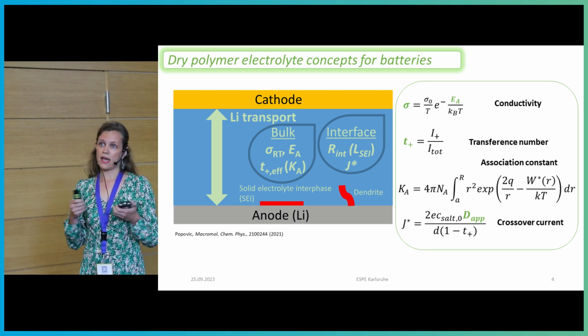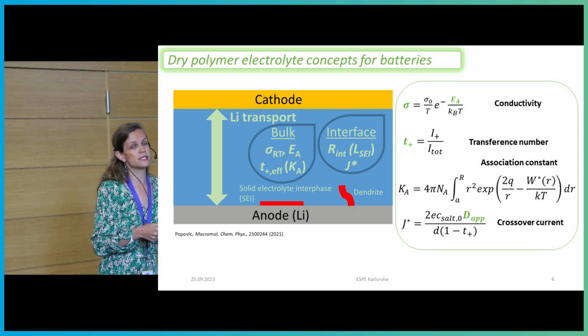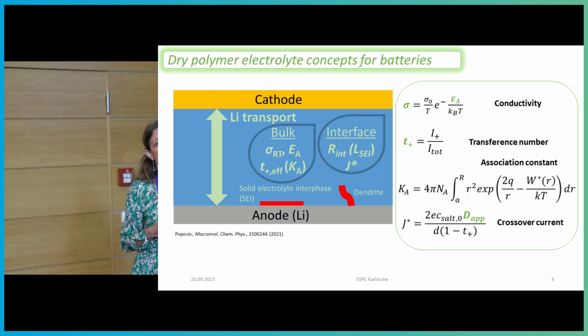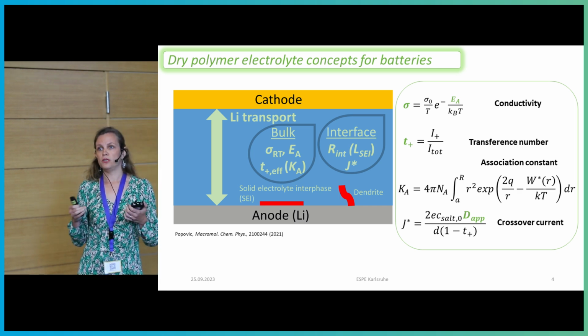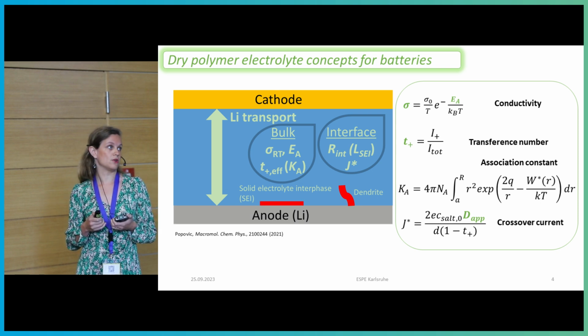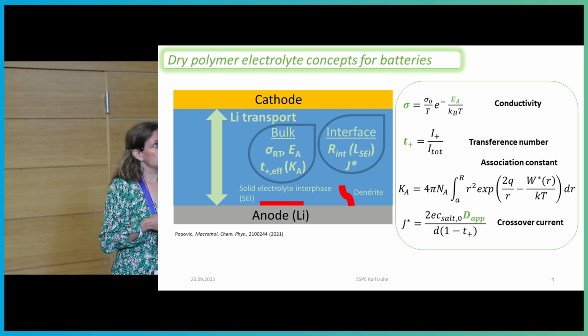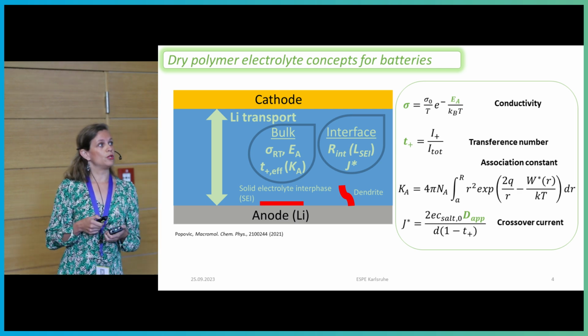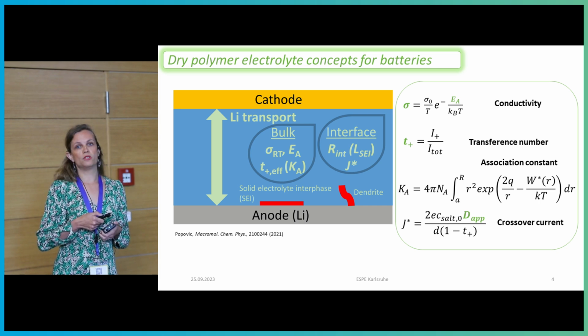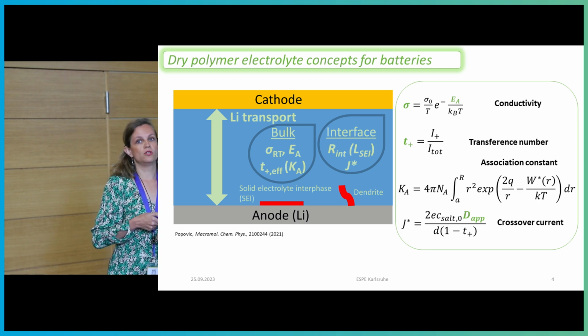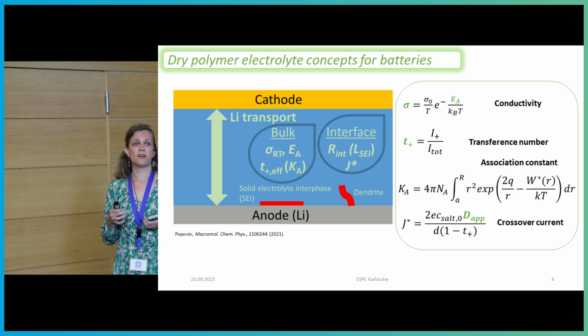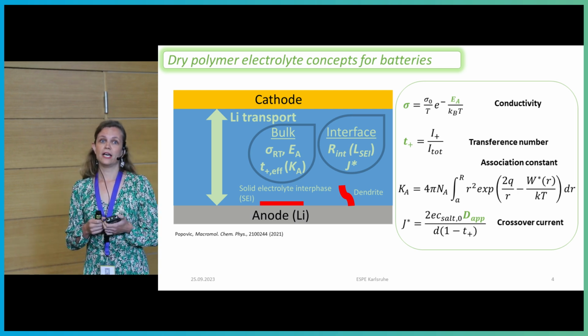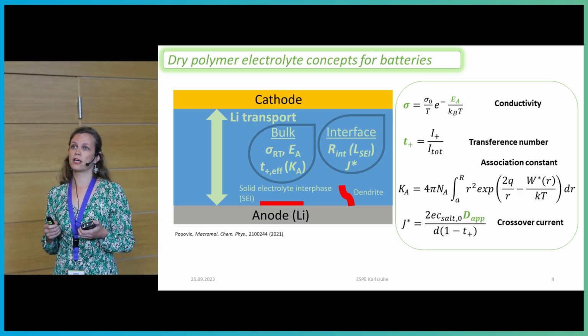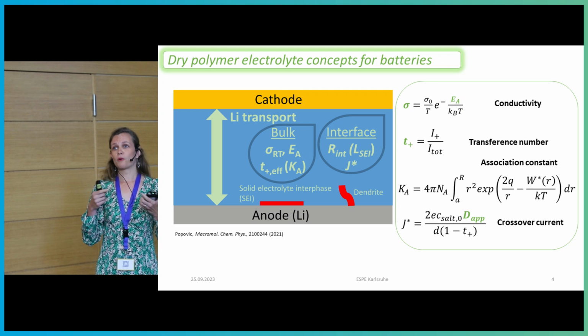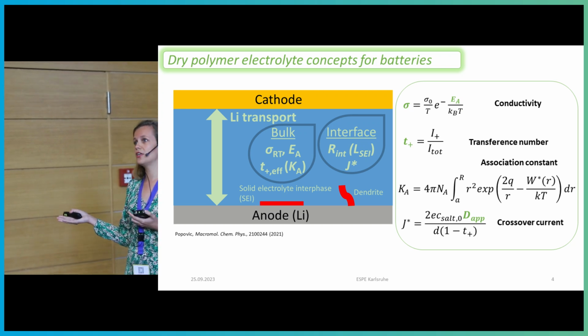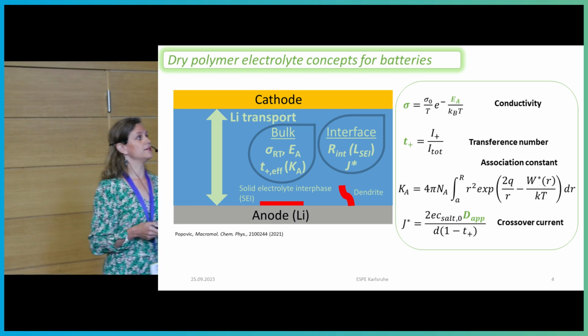So it's not only Coulombic interactions that actually count, it's all the other things that are described in this work here that are related with the entropy of these highly concentrated electrolytes. And then finally, we need to have something that gives us a nice chemistry at the interface, but also allows for relatively high crossover current so that we don't end up with dendrites very quickly. And that is again related with the diffusion coefficient of our electrolyte. So it seems like a very complex thing that we have to do: tune all of these parameters in order to have a really good electrolyte. And unfortunately, many of these parameters are correlated in a negative way. So we are trying to improve one thing, and then we are actually making another thing detrimental.